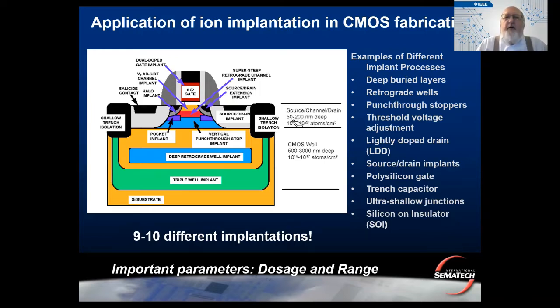500 angstroms deep was our target, and middling density to high in the contact area. But channel engineering was a big technology that people were going into. You would have retrograde channel up close to seal the channel in. You'd have punch through and pocket implants to make sure the leakage currents were minimal. Then we would have retrograde wells to tune the fields and the amount of leakage that you might get on both, that would seal in these. By the time you get to where we're headed, there are 9 to 10 different implants.